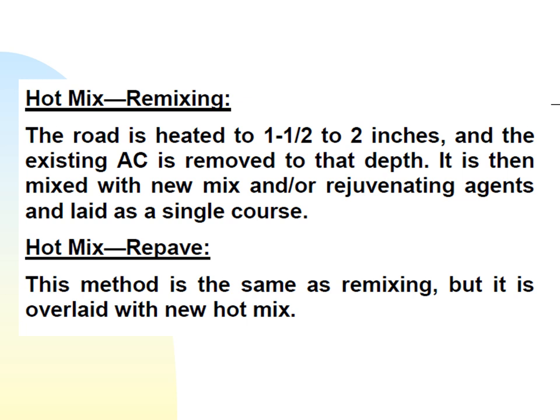Well, on this particular slide, you can see hot mix remixing. The road is heated to 1.5 to 2 inches and the existing asphalt concrete is removed to that depth. It is then mixed with new mix and or rejuvenating agents. Again, the term rejuvenating has been used over here, that means to render young again, and laid as a single course. Then comes hot mix repave. This method is the same as remixing, but it is overlaid with new hot mix.